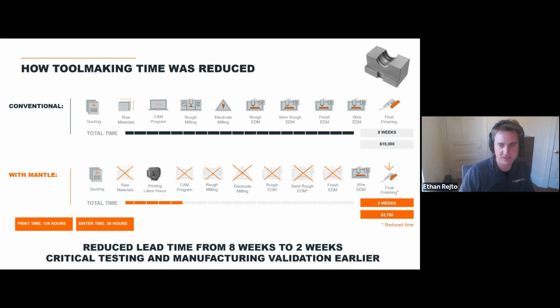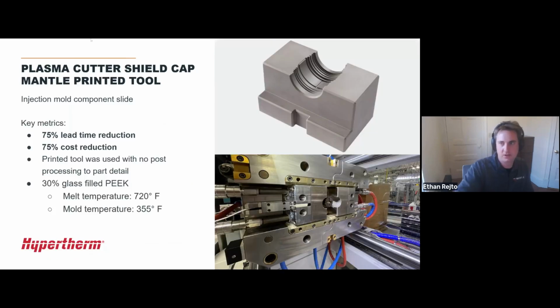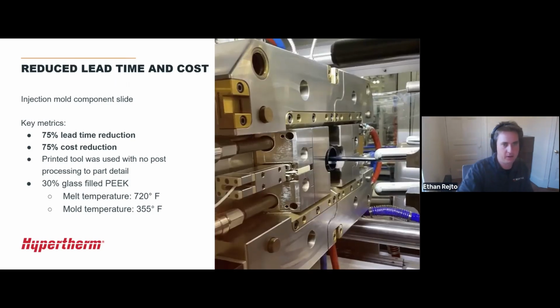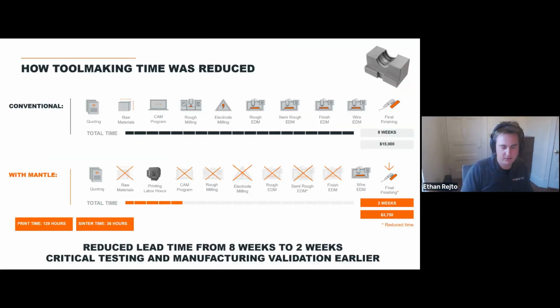The reason that they were able to save so much time and cost here was because, like we mentioned, they cut out all of the EDM time that would have been involved. If you look at the ribs on this component, all of these ribs would have required electrode burning, which is very expensive and very time consuming. They were able to remove all of that. They still did a little bit of wire EDM just for the taper on the slide, and then the grinding components, but still from 8 weeks down to just 2 weeks, thanks to their use of Mantle.